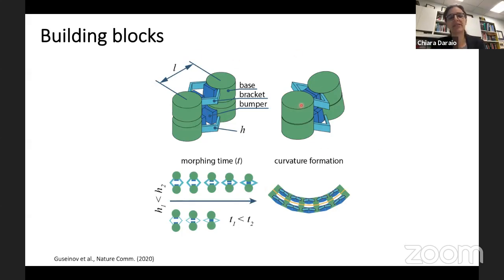Well, once we have these designs of these three elements, we can control the morphing time by varying the thickness H of this bracket. You can imagine that if, for example, temperature was your trigger, simply by diffusion processes, the time of actuation through temperature of thicker brackets is expected to be slower than the time it takes to actuate very thin and easy to bend brackets. And the curvature formation, the global curvature, comes from the assembly of these local bumpers, which control basically the contact mechanics at certain points.